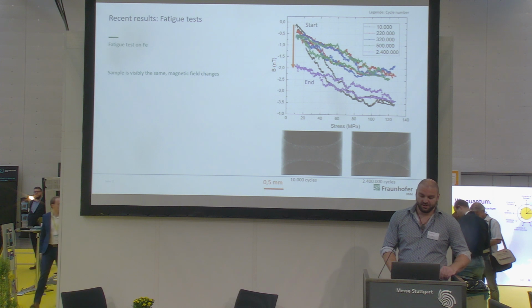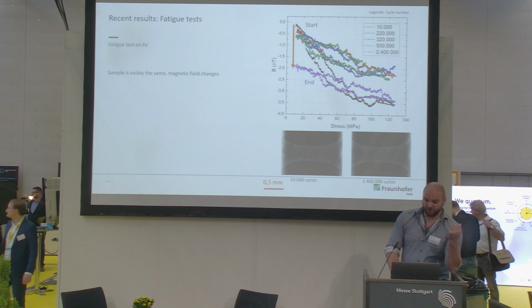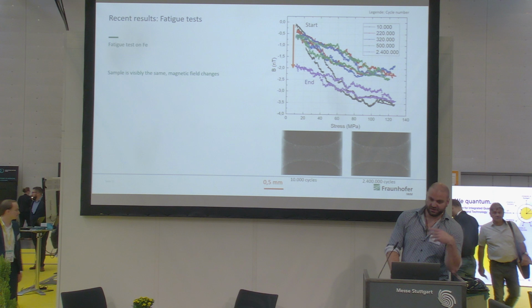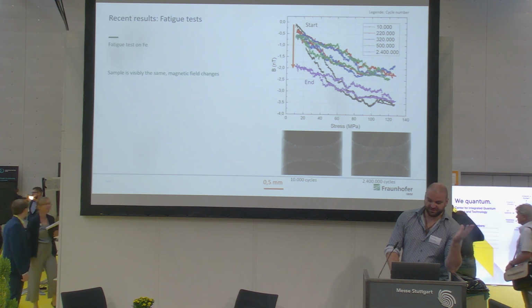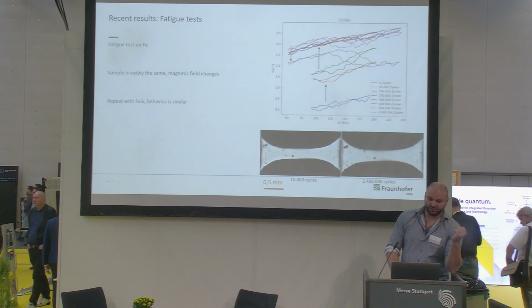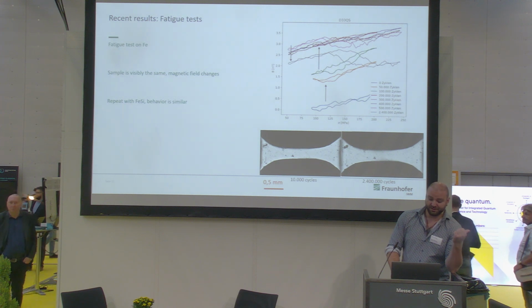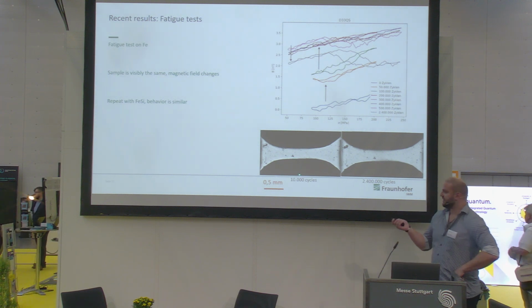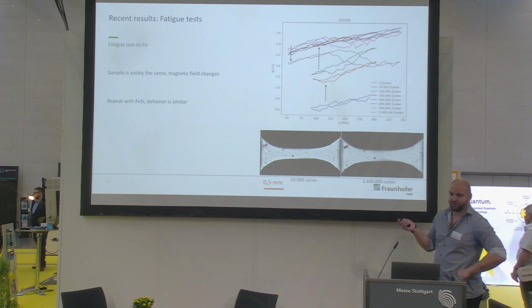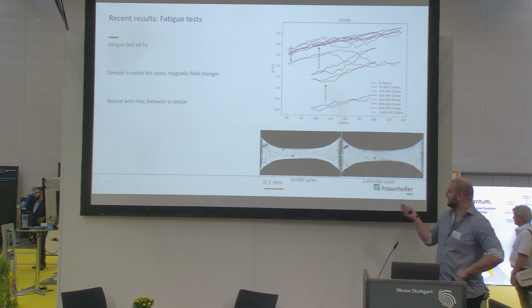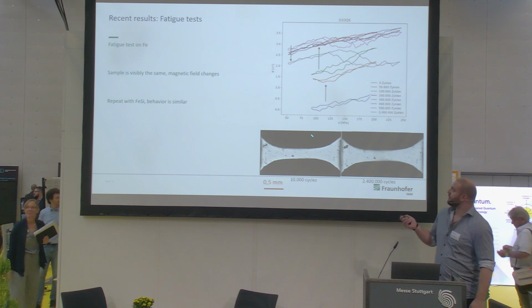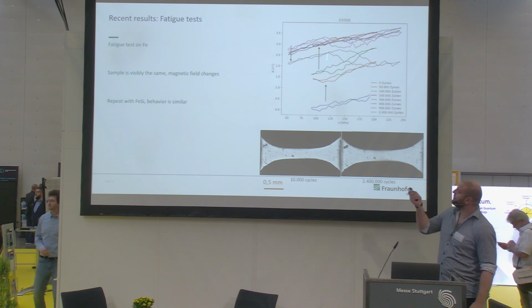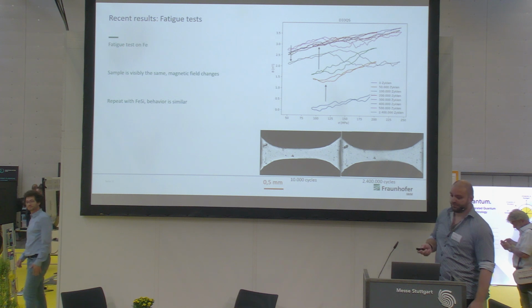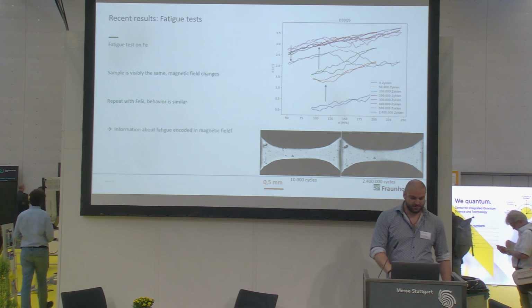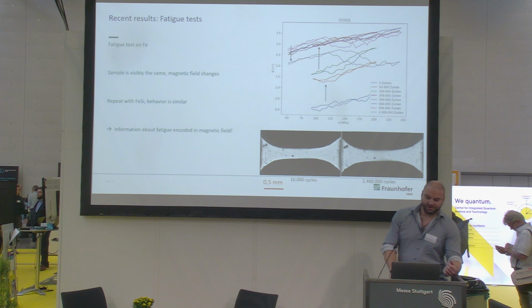So now we want to investigate this because this holds potential, of course, and we want to exclude all sorts of influences that we probably have on the material. So we use iron silicon from a single crystal, and we repeat this experiment. Here you have 10,000 cycles, 2.4 million cycles. The sample is a bit dirty, I have to admit, but technically it's still not damaged at all. But if you look again at the curves on the top, you can see it moves up, stays here for a while, and then moves down. Okay, so some sort of information about fatigue is encoded in this magnetic field.